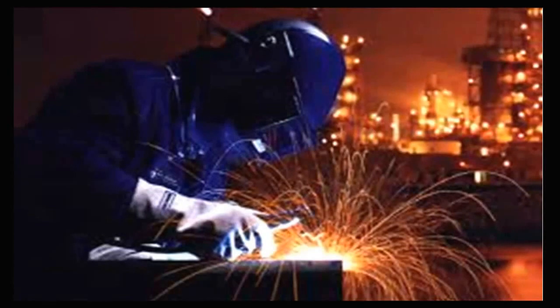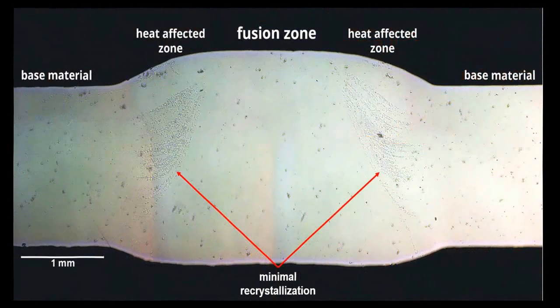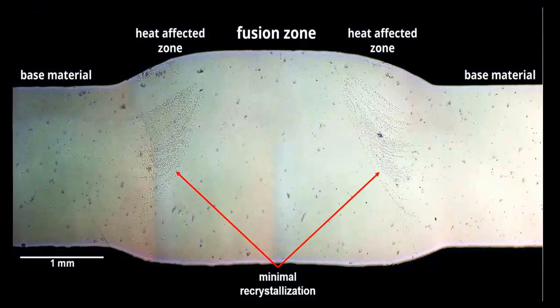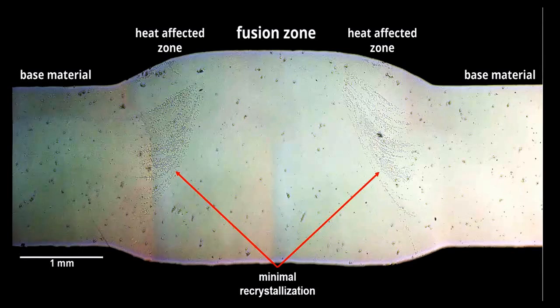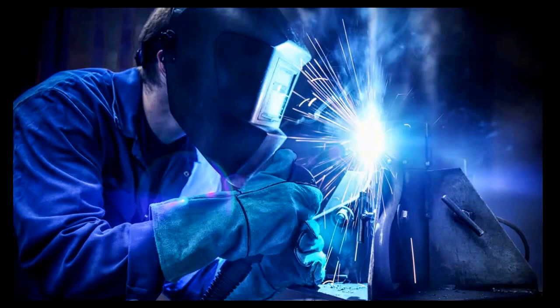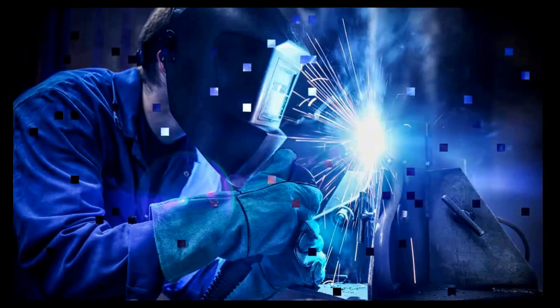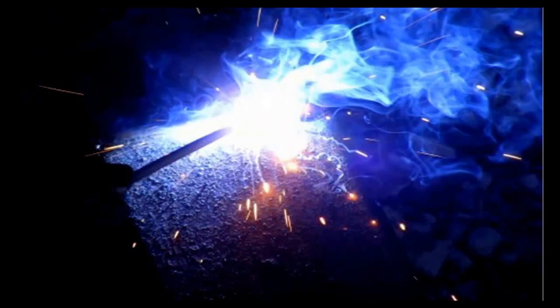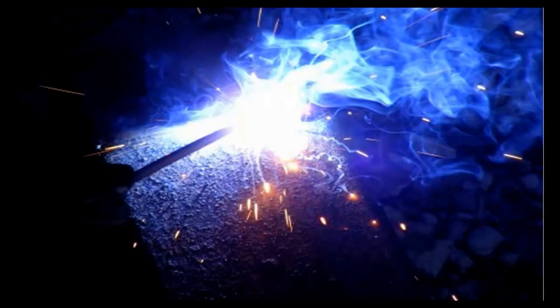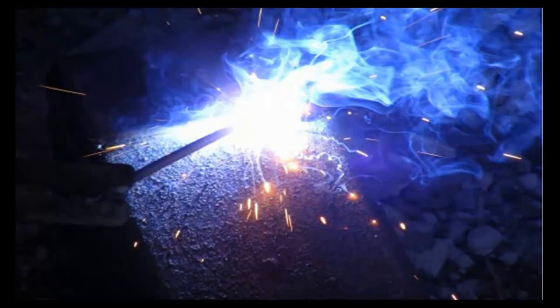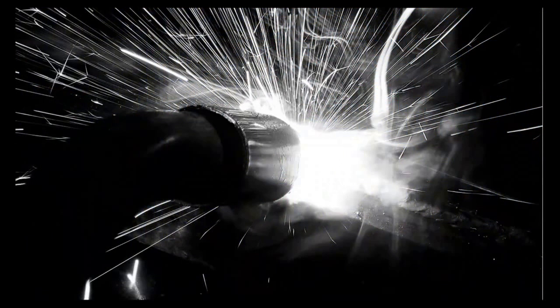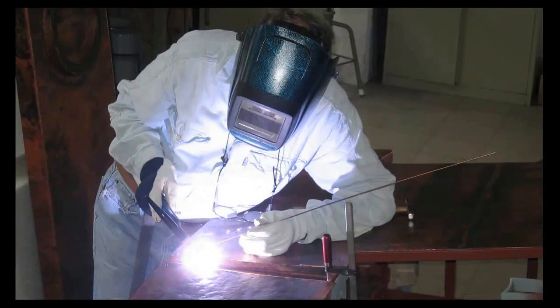Aluminum is usually protected by a thin film of oxide. Immerse the part in aluminum pre-cleaner, Eutectic 1002 pre- and post-cleaner, and all grease and oxides will be removed from the surface. The flux has to be very active, and if permitted to remain on the aluminum, it becomes active again whenever moisture or humidity is encountered. The white powder seen on the surface of an old weld is corrosion. The still active flux is dissolving the oxide and eating into the metal. Dip the finished parts into a hot solution of the aluminum pre- and post-cleaning solution.